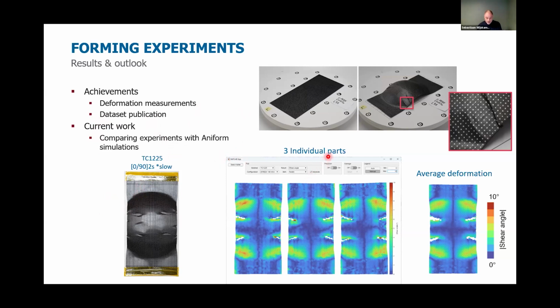Now, just to go back here, you see the analyzed deformation on the part. We take an average here. You see the white spots, those are dots that are missing because they are folded and not visible anymore. So this is what a typical deformation analysis looks like.